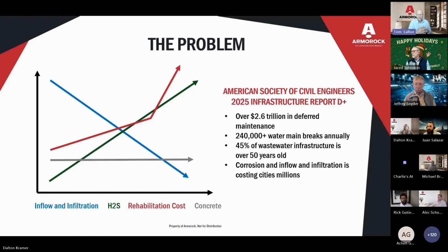And the problem really is that the solutions that Jared talked about that pre-Armorock explored all relied on Portland cement-based concrete. Linings and coatings still have Portland cement-based concrete as a core ingredient to the product. And Portland cement is susceptible to H2S corrosion. It is corrosive. So over time, anything that is done that involves Portland cement will not be successful. So what Armorock has done, and what the polymer concrete industry has done, is engineer a better solution by eliminating Portland cement from the material matrix to actually have a product designed for the environment. And we'll go through those key ingredients now.